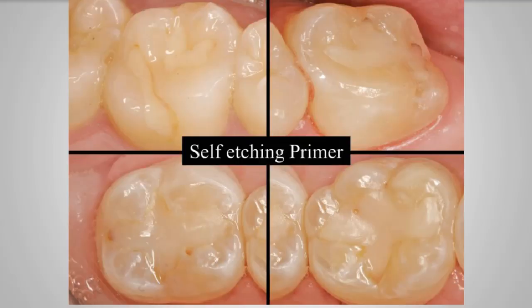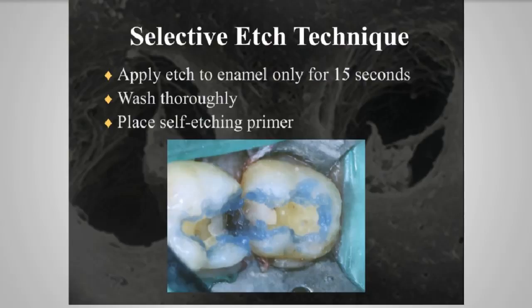So this is what I have observed in my patients when I have used certain self-etching primers, and patients come back for recall. You can see the brown line, you can see bubbles, you can see all kinds of problems at the enamel surface. So what has developed over the last few years is this concept of the selective etch technique, because the self-etch technique is least technique sensitive. That is, it's less affected by having the proper moisture in the dentin, and it works better consistently, but it does not do the enamel as effectively. So if we acid etch the enamel and not the dentin, that's the best of both worlds.